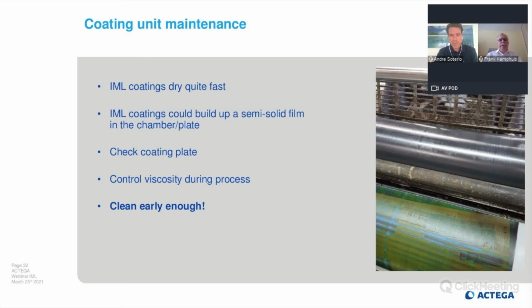The same we recommend for the coating unit. So what I explained, the coating dries very fast, and if you have a stop for several minutes or at the end of the job, please at first clean your coating unit, so that you avoid drying of the coating on the roller and on the plate. Check that your coating plate is really clean enough, and clean early enough.